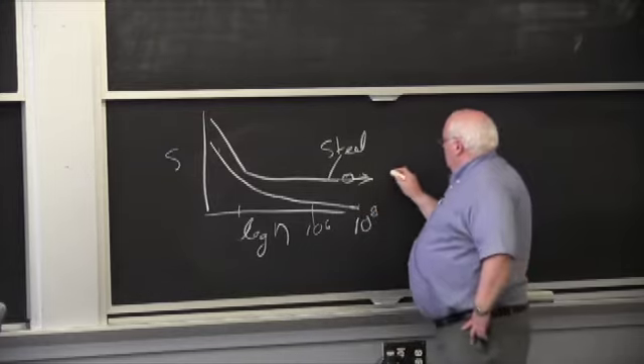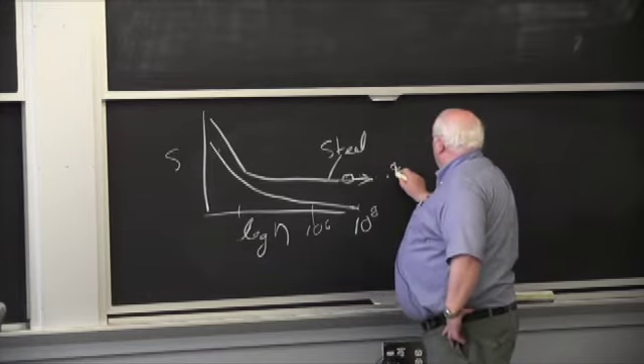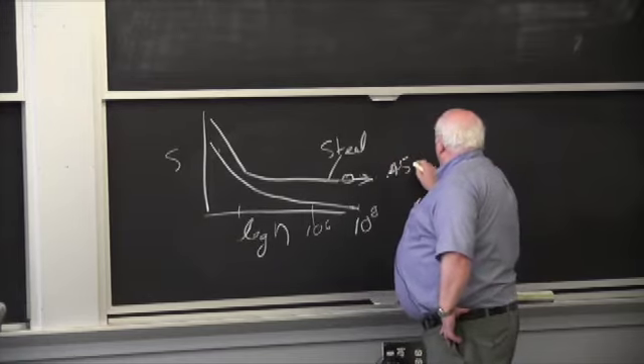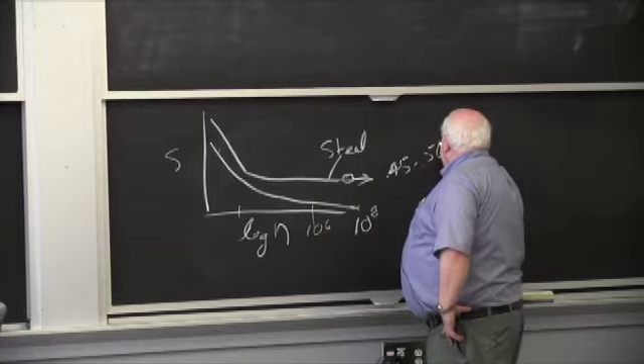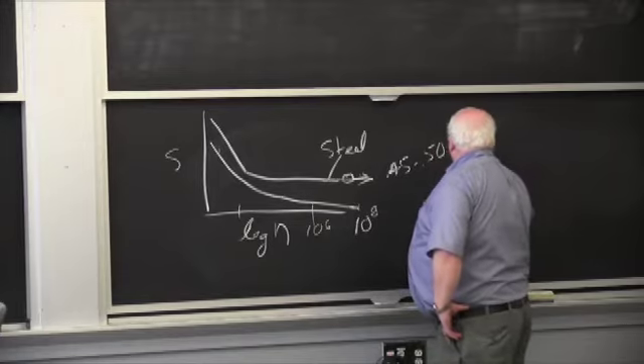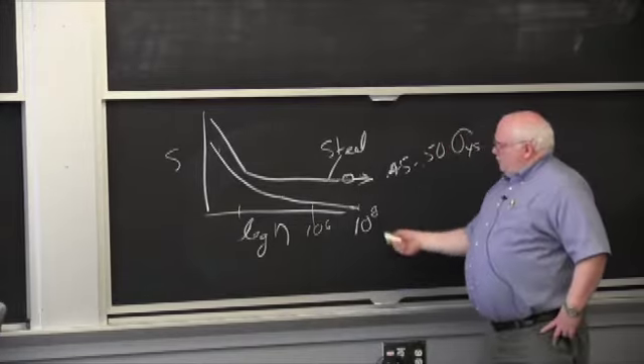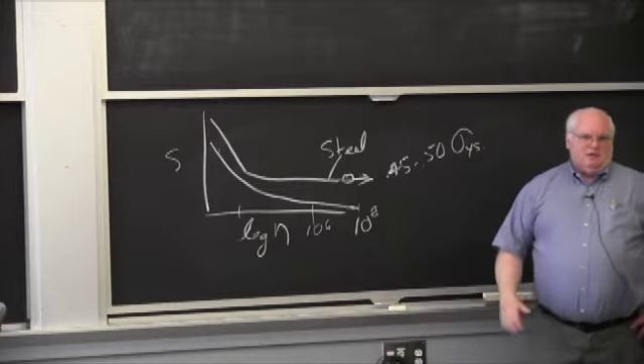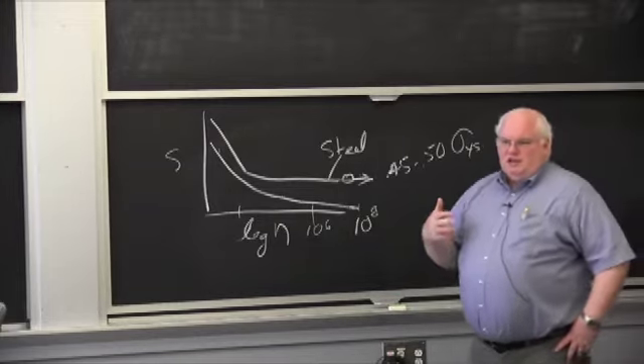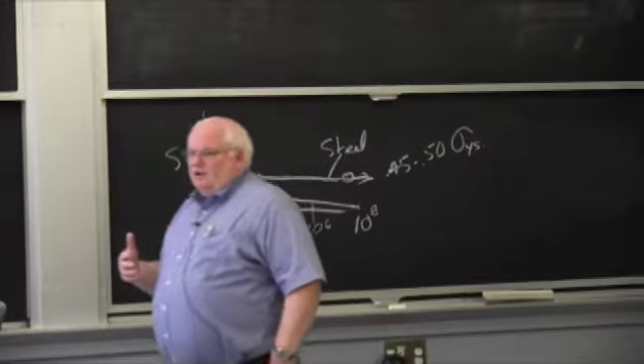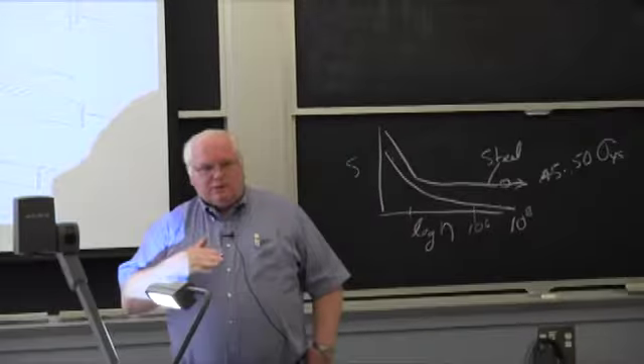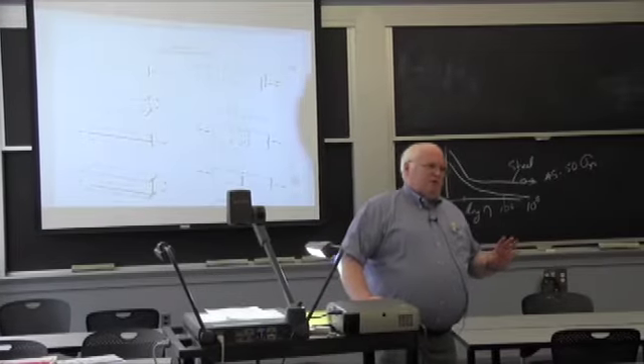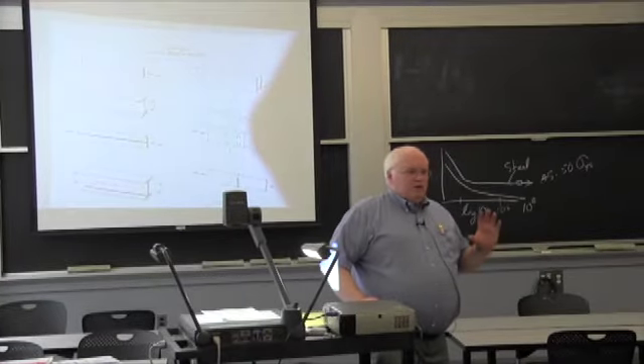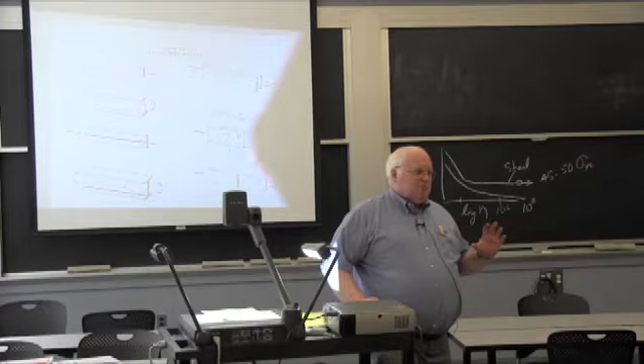For steel, the fatigue limit is somewhere between 0.45 and 0.5 of the yield stress. For aluminum, there is no fatigue limit. If you fatigue the aluminum long enough, the acceptable stress level will keep going down. This was a big problem for introducing aluminum wheels in trucks, okay?